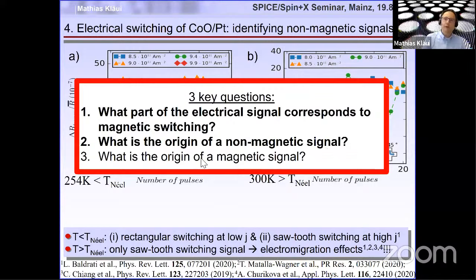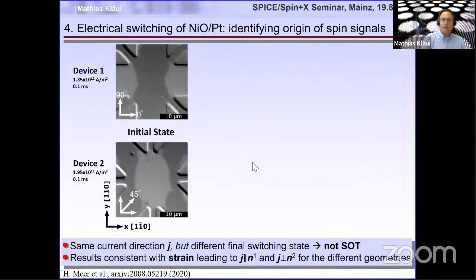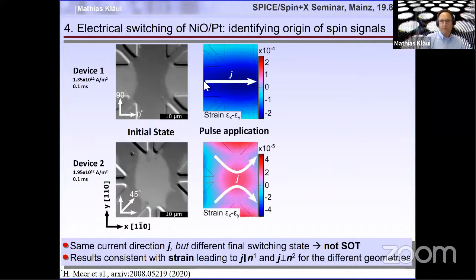But the question is, what is the origin of the magnetic signal? To check if this is spin orbit torques, or, as some colleagues suggested, some magnetothermoelastic effect, we investigated different devices where we injected current pulses either flowing from left to right in a straight pulse, or injecting the pulses across these 90 degree corners, which in the center should give you the same current density, i.e. the same spin orbit torques.